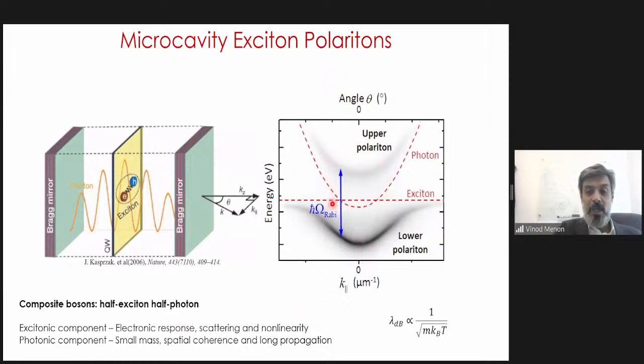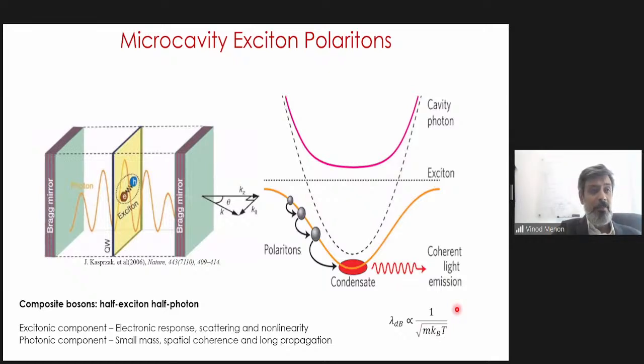The other big motivation was driven by the cold atom community. People were very interested in whether you can get condensation of these polariton states. And this was primarily because the temperature at which you get condensation is dictated by the mass of the particles and indirectly the de Broglie wavelength. And it turns out that because the mass of these guys is much lighter than the cold atom system, you should be able to get condensation at elevated temperatures. And in fact, this was the work that was actually driving the early part of 2000 to 2010. The work in this field was primarily driven by this whole idea of condensation in the system.